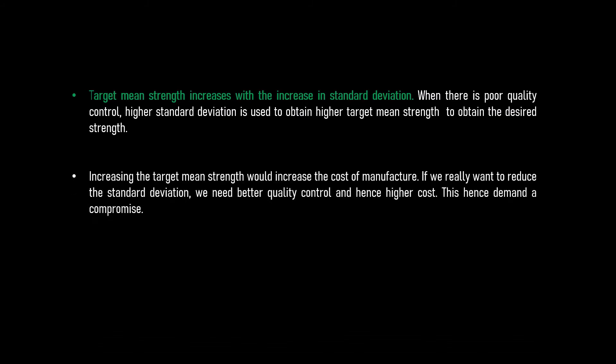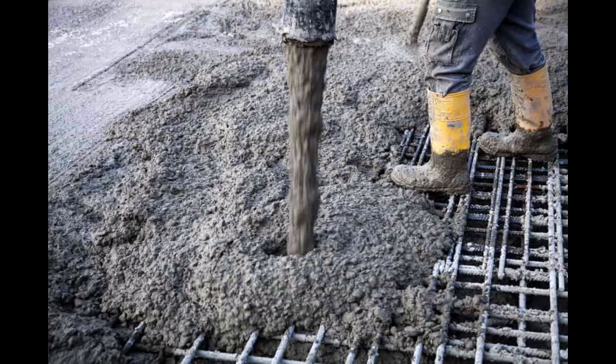In UK, the value of standard deviation is mainly between 4.5 and 7 N per mm2. A value of less than 4 N per mm2 is seldom obtained due to the behaviour of different materials that are used for the construction of the concrete. This is why quality of materials used in concrete mix design really matters to the design strength.